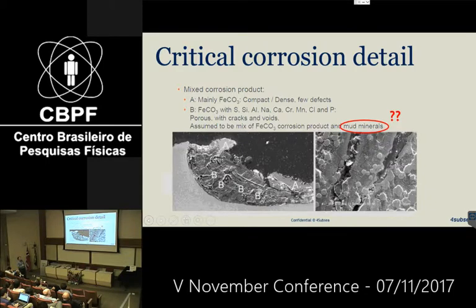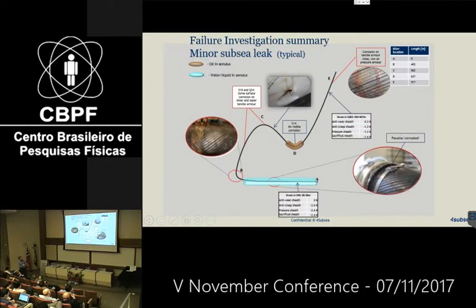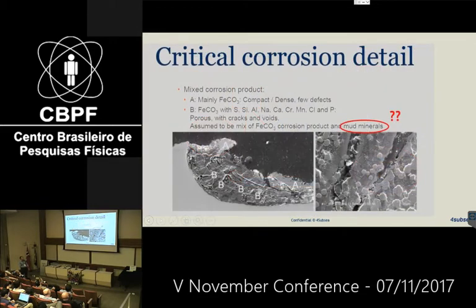There were also some peculiar particles found in the annulus. That was in an area where no outer cover damage had been reported. A lot of investigation went into that, and we found that some of these mud minerals had a density more or less equal to water, so they were more or less floating for months. So we were saying that maybe that had come in as a result of a damage during installation, but there was no damage found. Then we went back and did more inspection, and found a micro damage somewhere here, which was probably the cause. So we had a situation where some minor defect during installation had resulted in not having a reliable protection against CO2 corrosion. So that's one example.